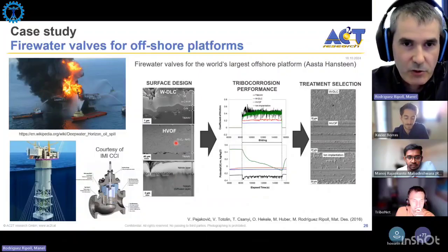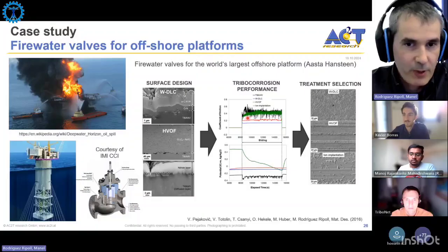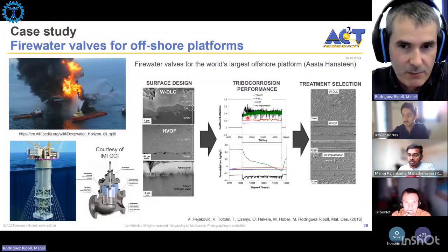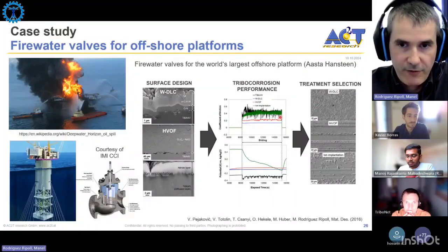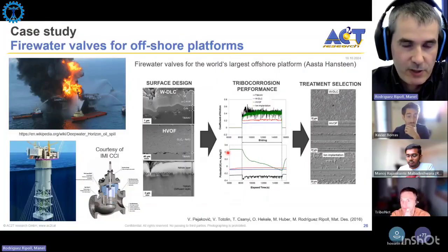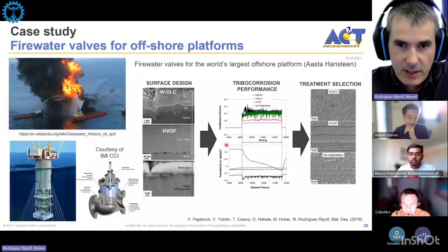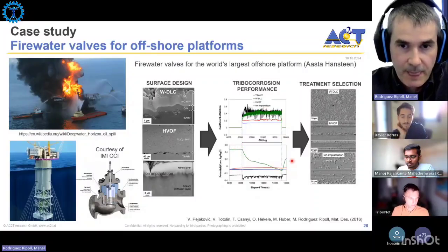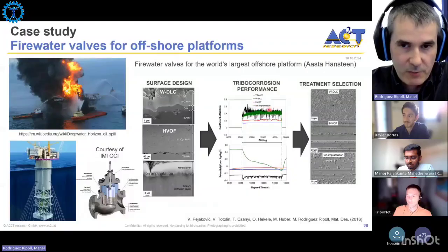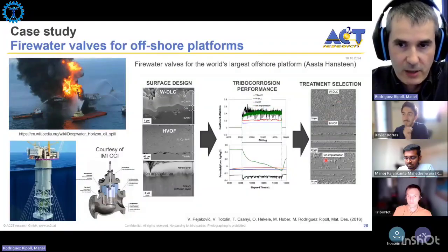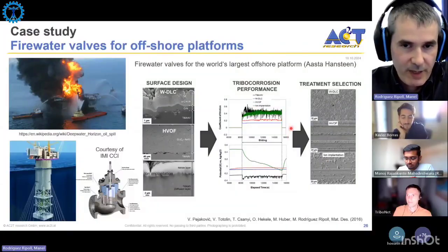Basically, what you can do with these different materials, using also titanium as a reference, is make open circuit potential experiments, as we have seen before, very simple. From these experiments, you can get the evolution of friction as a function of time for the different surface treatments, and the evolution of the open circuit potential as a function of time. You see here the different OCPs before rubbing, during sliding and after sliding. Based on the OCP behavior, the friction behavior, and the total wear that you measure at the end of the experiment, you can use this data for making suitable selections.